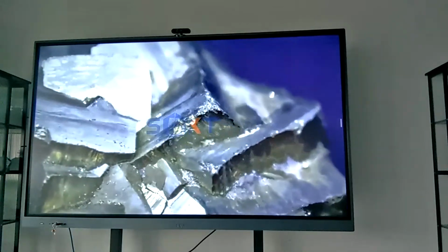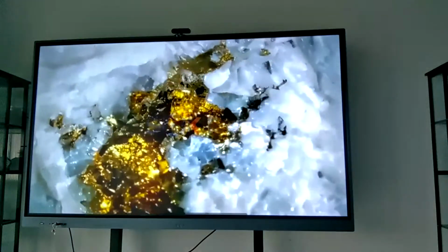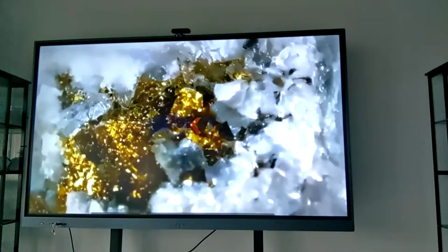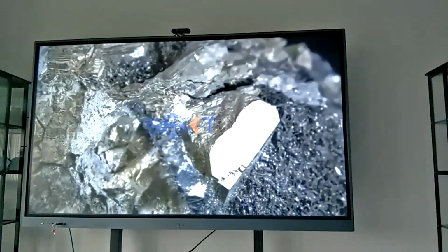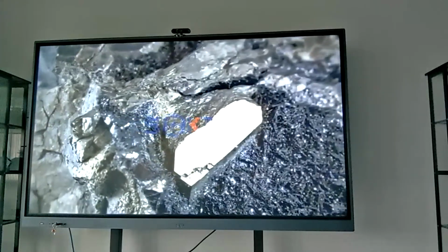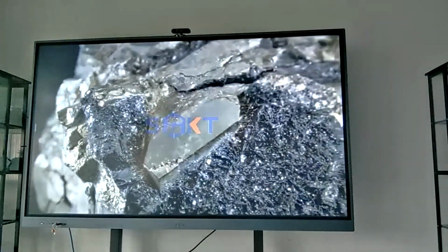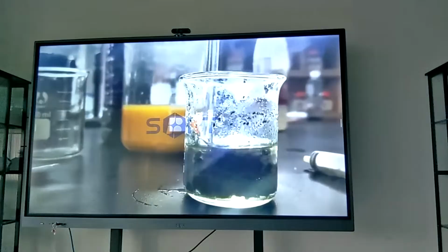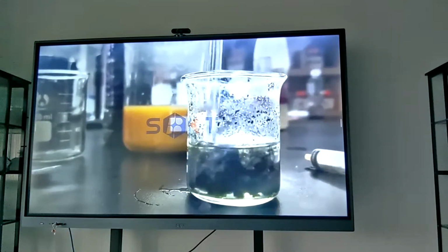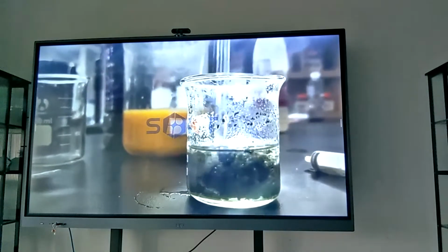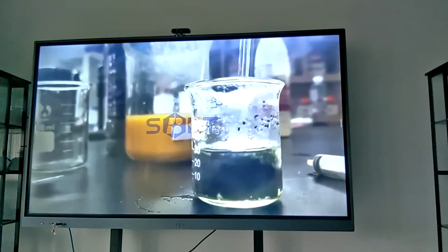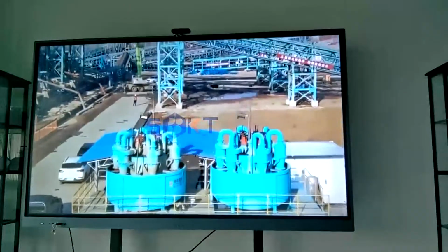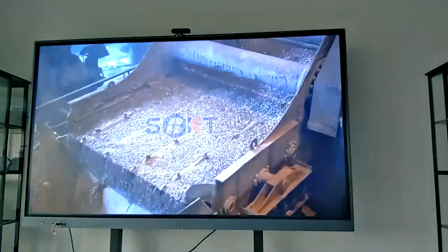Process selection has so economic means: obtain copper gold concentrate through flotation. Heap leaching is not suitable because gold is in sulfide, so heap leaching cannot extract it. However, the oxidized zones, the surface layers of the deposit, are greatly suitable for heap leaching.